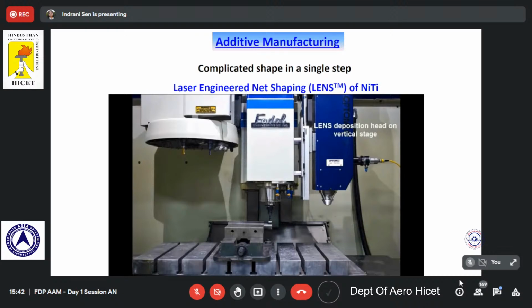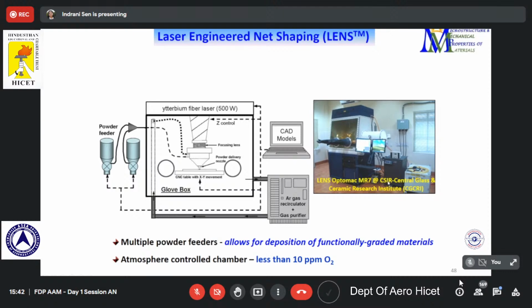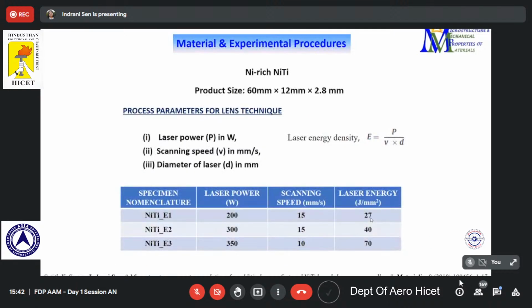So every layer it can alternate its direction of motion, and this can be set to 90 degrees or 45 degrees, 60 degrees, based on the requirement. That is to maintain some uniformity in the structure so that it is not getting textured. And once formed, it is removed, and then the substrate has to be removed. This is a machine placed in the Central Glass and Ceramic Research Institute, which has been used here. All the operations are done inside the glove box.